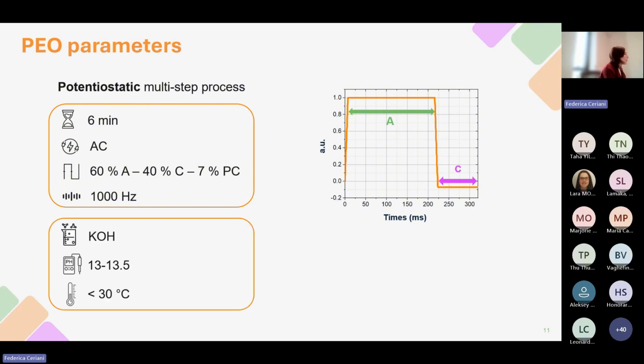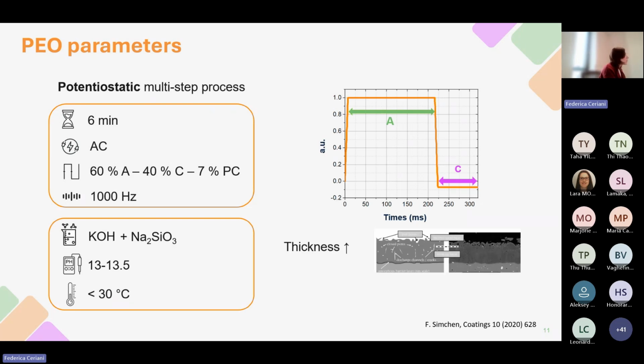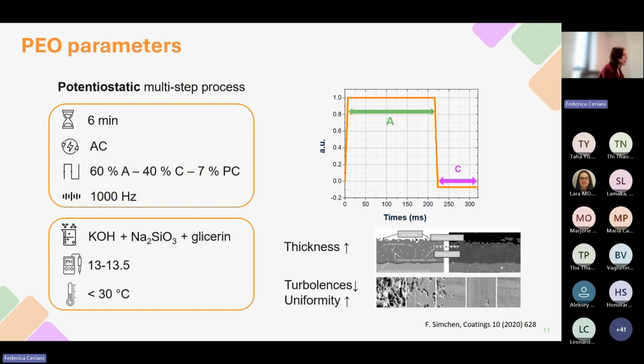For the chemical composition of the electrolytic bath, I work with an alkaline solution with a pH ranging between 13 and 13.5, mainly based on potassium hydroxide, with additional sodium metasilicate to favor the formation of a thick oxide layer, and glycerin to reduce the turbulence within the electrolytic bath, promoting the formation of a uniform coating.